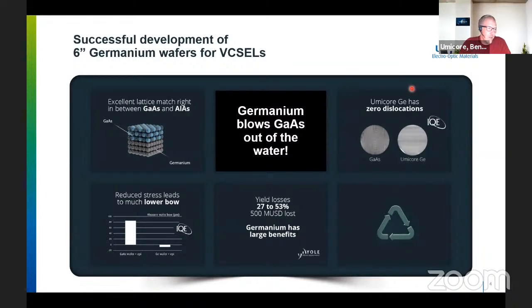Another point which is important is the dislocations. The limitations of gallium arsenide are the fact that you have certain dislocations, and the bigger the surface of the wafer becomes, the more difficult it becomes to control the amount of dislocations. That's why 6-inch is already a stretch. 8-inch is becoming very difficult. As I've mentioned, we don't have any dislocations. So if the industry wants to move to larger sizes, for instance by making bigger VCSEL arrays, which are going to be needed in LiDAR applications, for instance for autonomous vehicles, there the bigger wafer sizes are going to become much more important, and germanium could be an interesting solution.